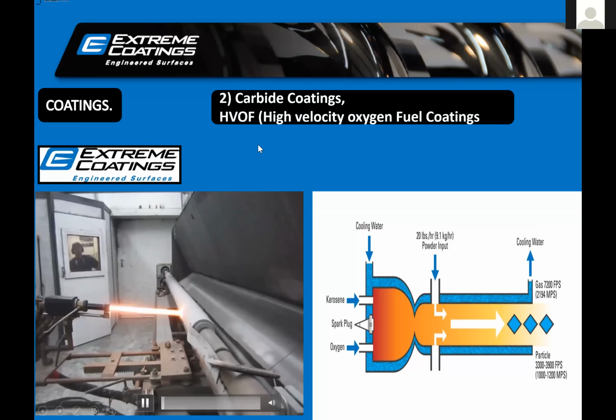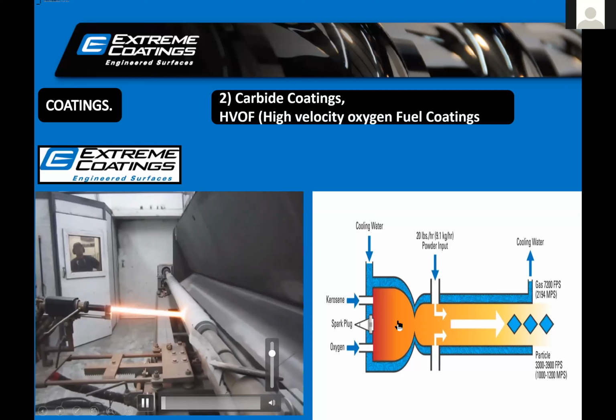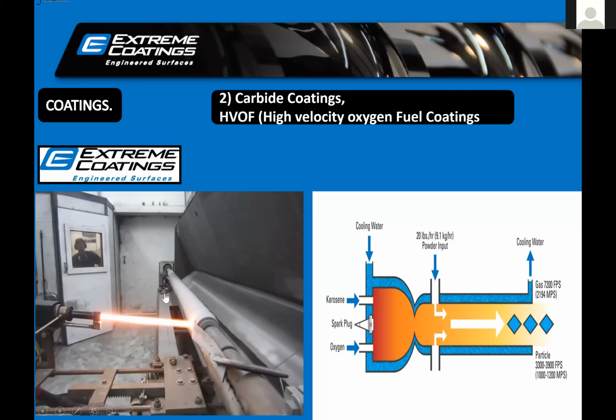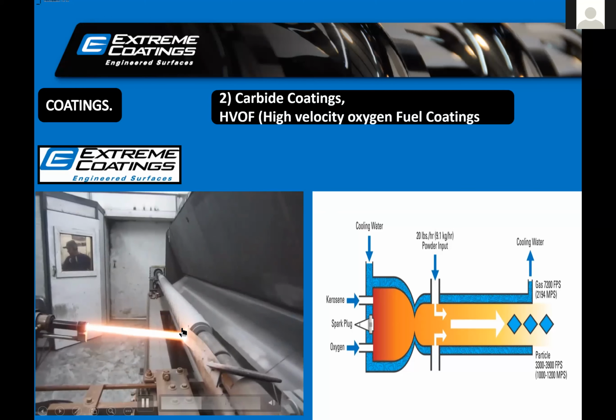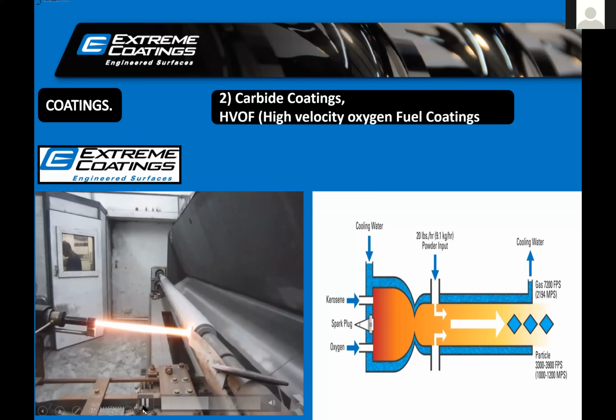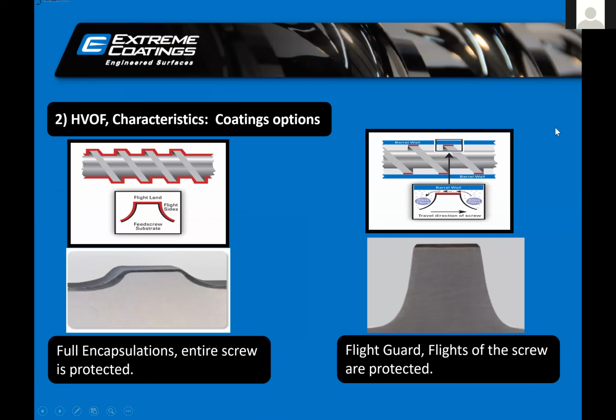So what is happening here: there is a high velocity oxygen fuel flame, and the tungsten particles are poured from here, and with very high strength they get embedded on the steel surface. Now, what is the advantage of this? There are two advantages. One is if you are looking to protect only against abrasive and adhesive wear, which mainly happen on the flight top, we can put coating only there. And if you have polymers which require attention on all three aspects, corrosion, abrasion, adhesive, then we have full encapsulation also, where the tungsten carbide layer can be on the entire surface of the screw. So one is called flight guard, one is called full encapsulation.